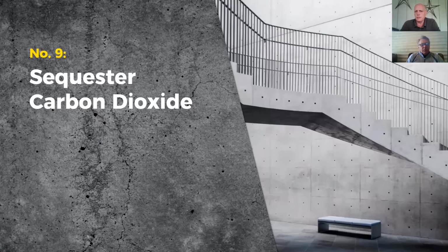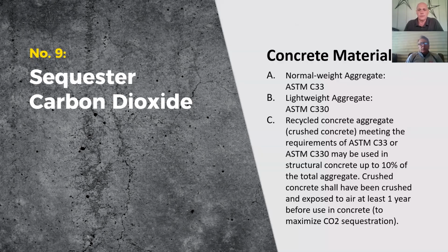For in-service concrete, carbonation is a relatively slow process with many dependent variables. The rate decreases over time. And this is because carbonation decreases permeability and carbonation occurs from the surface inwards, creating a tighter matrix on the surface that makes it more difficult for CO2 to diffuse further into the concrete. While slow, the carbonation process does result in an uptake of some of the CO2 emitted from cement manufacturing, a chemical process called calcination, where CO2 is emitted. Theoretically, given enough time and ideal conditions, all the CO2 emitted from calcination could be sequestered via carbonation. We don't necessarily have ideal conditions, but obviously exposed concrete's a big part of it.